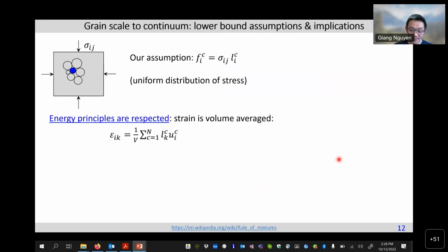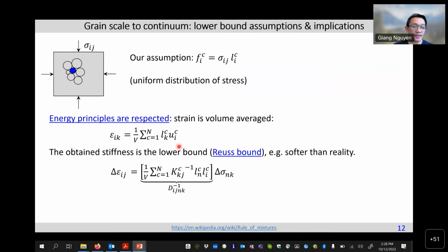So now, if we assume this and use the energy principle, we get the link between macro strain and the relative displacement between two grains in contact with each other. We get the prediction of the macro stress-strain relationship that has the behavior at the grain scale, the individual behavior, in this case. K here is the stiffness, and L here is the branch vector. That is basically, for spherical grains, the normal to the contact.